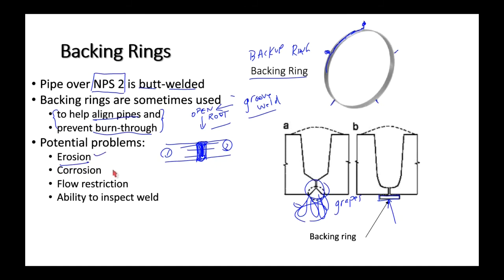First of all, there's a place where fluids can swirl around and wear away, so we can get erosion. And we saw earlier caustic gouging going on beneath the backing ring. That was one of the slides that I showed back in corrosion. Also a little bit of a flow restriction, more turbulence and a diminishment of the cross-sectional area of the pipe. And it makes it more difficult to do non-destructive examination on the weld. When are they used? Like I said, when specified by the design engineer.